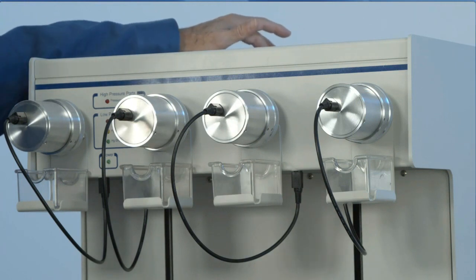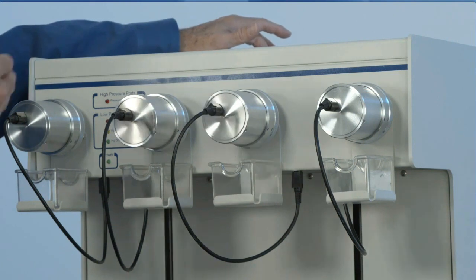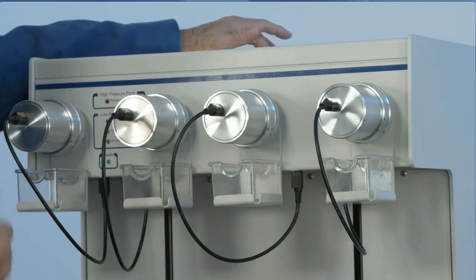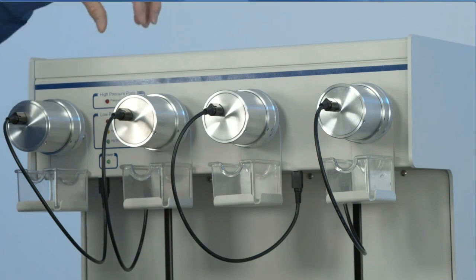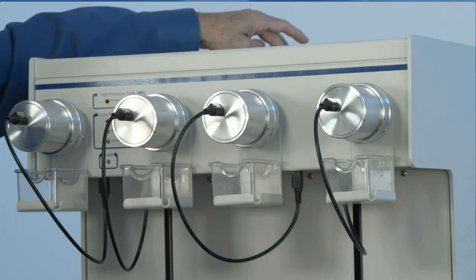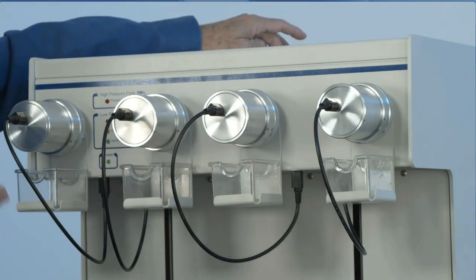And if that temperature rises above a threshold that the operator can set, it'll warn the operator. A message will appear on the screen saying, hey, it's getting warm inside the cabinet. Again, when working with mercury, we want to keep temperatures down because we want to slow evaporation of any mercury that happens to get loose and get stray from us. We also use that temperature sensor to determine the density of mercury that is surrounding the sample when we fill it, and that helps us in getting our bulk densities, as we'll explain in the software in just a few minutes.